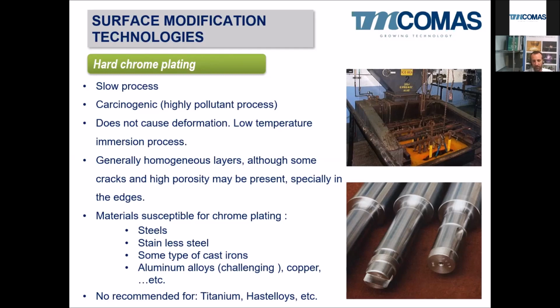improved. It has been overcome by thermal spray coatings, tungsten carbide. It has been overcome by laser cladding of ultimate, for example, coatings for piston rods in offshore. So it was an ancient technology that has a lot of limitations, but from time to time, some parts still arrive to our workshop with hard chrome plating, and we are replacing them by our coatings or by our other more technological advanced solutions. What materials are susceptible for chrome plating? Steel, stainless steels, some types of cast irons, aluminium is challenging to make this plating in aluminium, coppers. It's not recommended for titanium, Hastelloys.